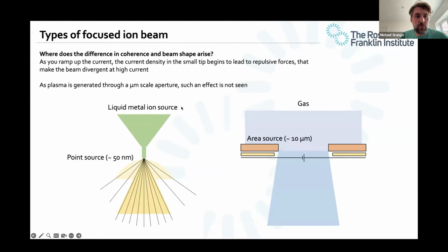Part of the nature of the two ion sources: LMIS, which is gallium ion sources predominantly because they have a low melting temperature and they're relatively stable. These are a point source, so you're talking 50 nanometers or so. And that means you can focus your ions to a very fine point, and you can get a very fine starting point for focusing your beam through the ion column. In contrast, when you have a plasma ion beam, you're using essentially an aperture, which is an area source. So you have a much larger point at which you're extracting ions, and that's why you have different coherence and beam shape. But obviously, the more you extract from that tip, the more these ions, which have charge, will repel one another, and that's why when you try to extract very high ion currents, you get a divergent beam in the case of gallium.